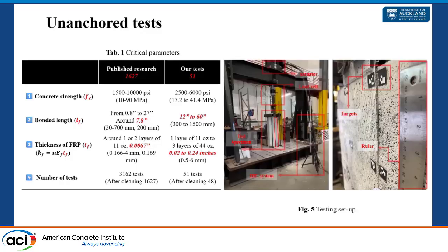And here is our test setup. We can clearly see that the specimen was anchored by a steel frame, and the load cell helped to pull the FRP ties, and the actuator transferred the load and displacement data to computers. We also adopted 2 cameras here for 3D DIC, serving as a data acquisition system, which also helps us measure all the plane deformation if it happens. And we attached targets and rulers to better calibrate the results from the 3D DIC system.